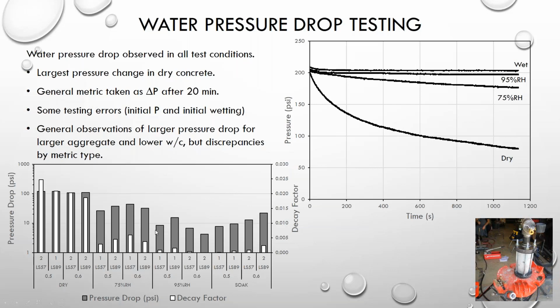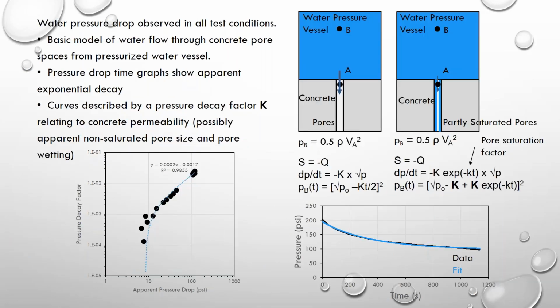So here's a graph showing again pressure drop for the different concrete types with the different outsized aggregates, water cement ratio, and different moisture conditions. The gray lines represent the pressure drop measured in 20 minutes, and the white bars represent the decay factor, which I'm going to describe next. So the decay factor really is trying to describe the signature of that decay line. And so when we correlate the pressure drop to the pressure decay factor, we see that they correlate very, very well. So I guess, how do we get this decay factor?